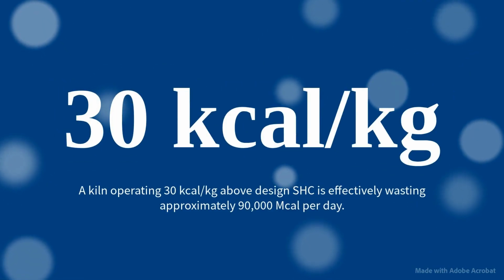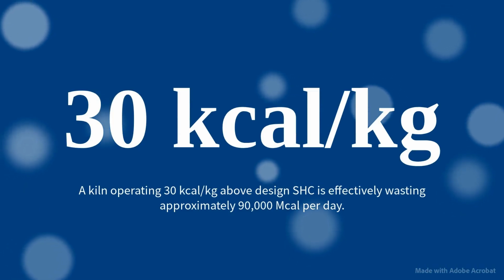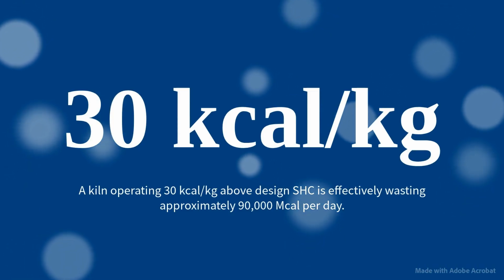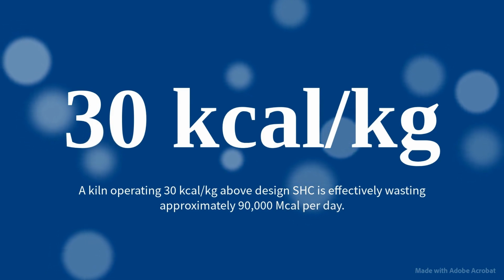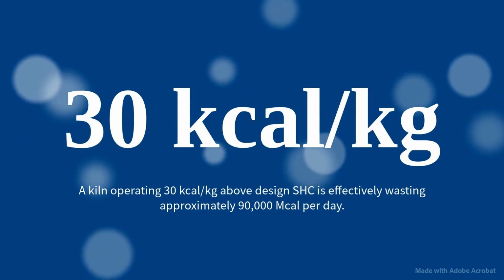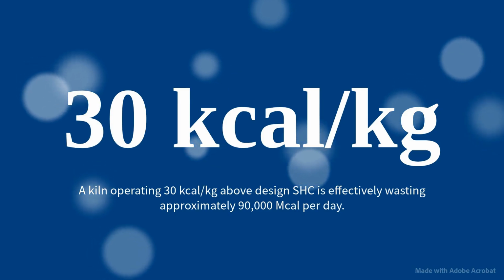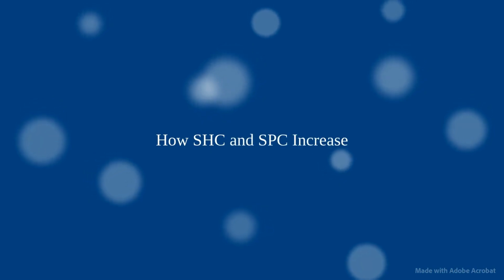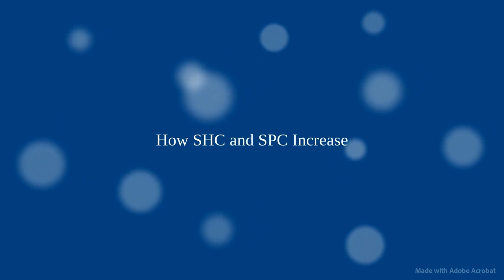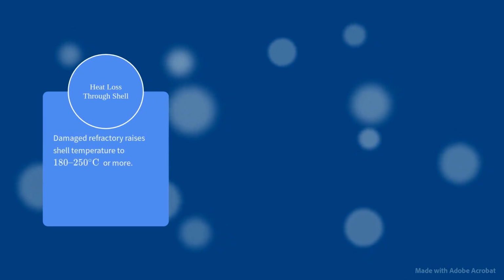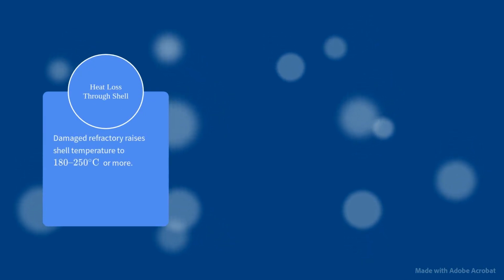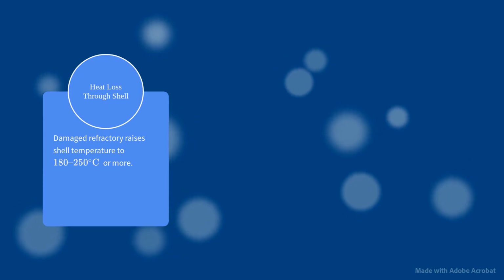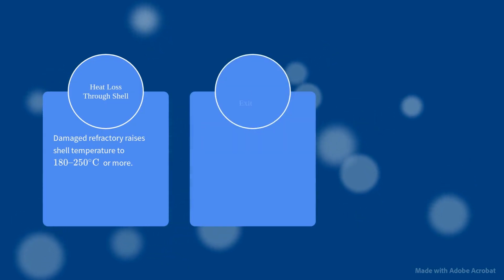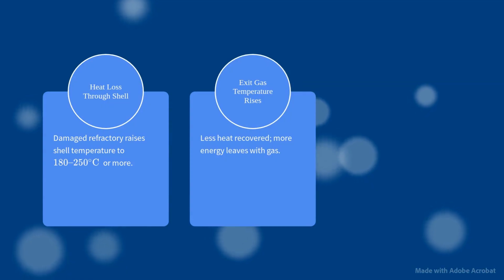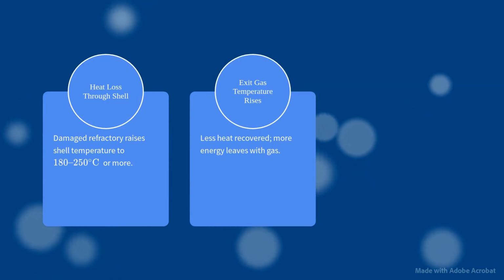A kiln running just 30 kilocalories per kilogram above its design-specific heat consumption is effectively wasting approximately 90,000 megacalories every single day. This shocking statistic reveals how even small efficiency losses add up to massive energy waste and cost. Here's how hidden cyclone failures quietly drive up both thermal and electrical energy consumption. Heat loss through the shell increases as damaged refractory pushes shell temperatures up to between 180 and 250 degrees Celsius or even higher. Exit gas temperature rises because less heat is recovered, meaning more energy escapes with the exhaust gas.